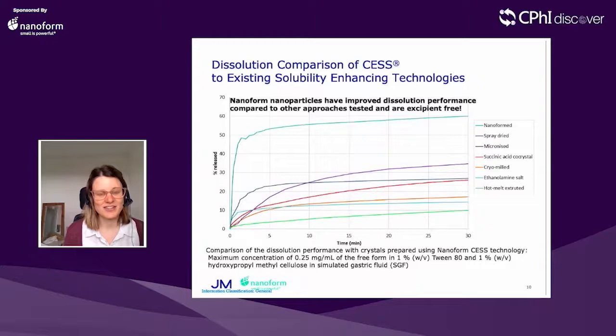So we can see that the nanoform nanoized particles had a much better dissolution profile compared with the other materials that we looked at. So we look at the initial dissolution rate of the nanoform nanoized material. It's much higher than the micronized material, as well as the amorphous dispersions prepared using the spray drying and hot melt extrusion, and also the salt and co-crystal forms that we looked at in this study.